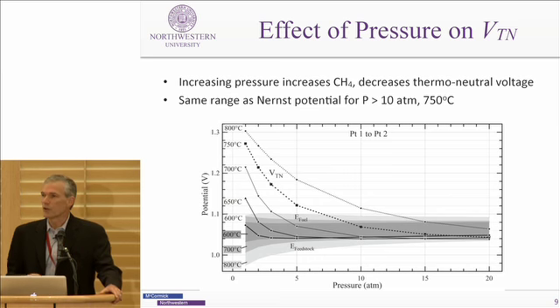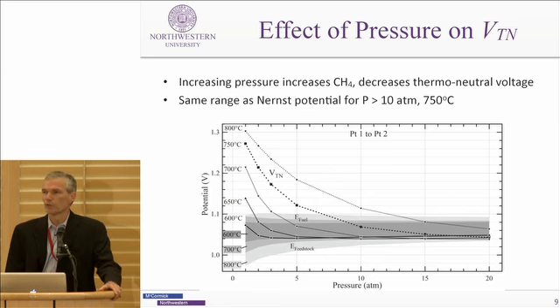And this plot is just showing that you can obtain a similar result not by lowering the operating temperature of the cell, but by pressurizing the cell. Okay? So this is showing this thermal neutral potential as a function of operating pressure of the device, you can see even at a typical operating temperature of something like 750 or 800 degrees centigrade, once you get up to 10 atmospheres or so, you already have a fairly low thermal neutral voltage.